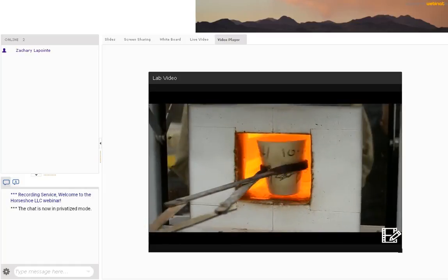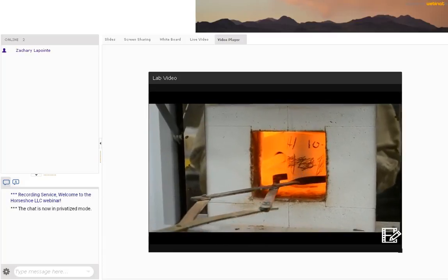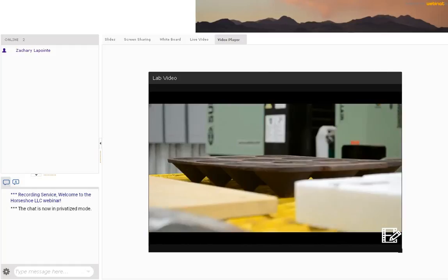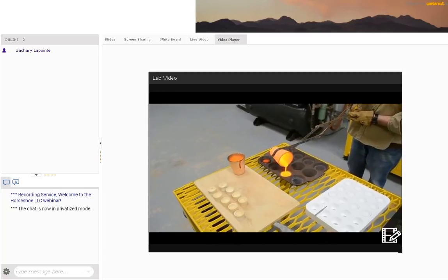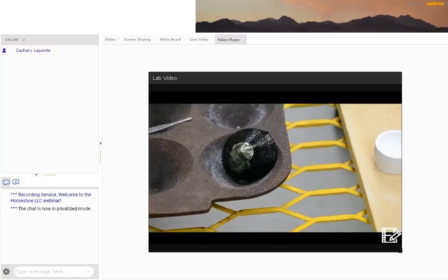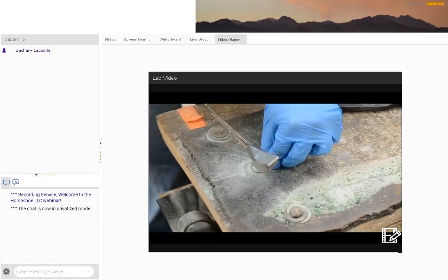The crucibles, as we see being placed here, go into an induction furnace at 1100 degrees Celsius for 1 hour for a reducing reaction to occur. This will pull all of the gold and silver into a lead button. Crucibles are then poured into a conical mold in order to separate the glass from the lead button. As each sample is processed, you can see the black slag layer and the lead button. The lead buttons are cleaned thoroughly and then weighed to ensure proper sample size.